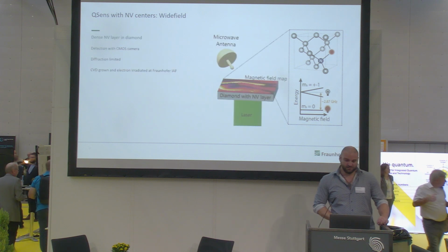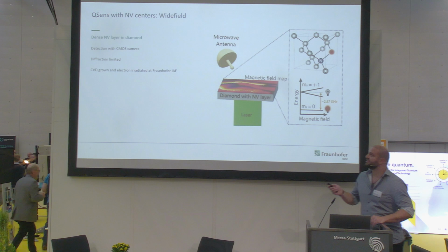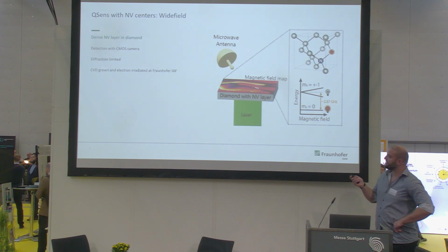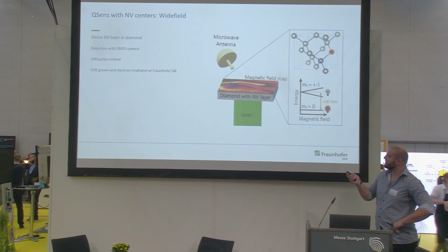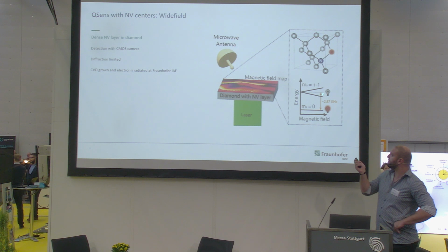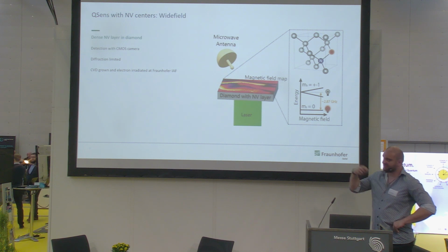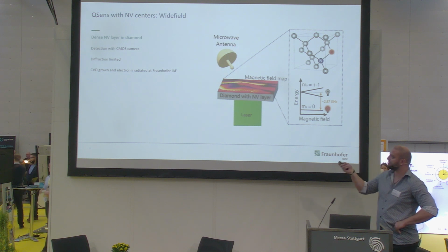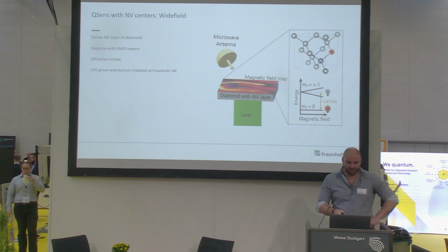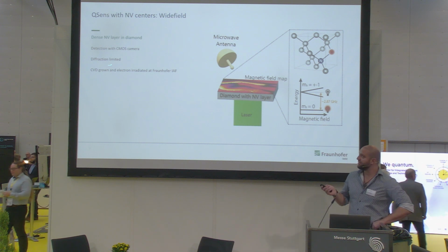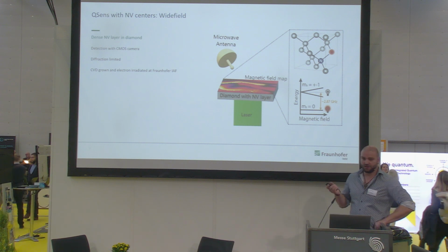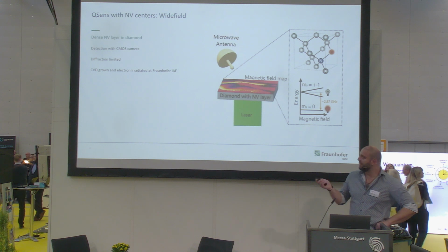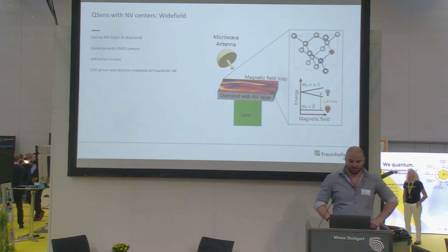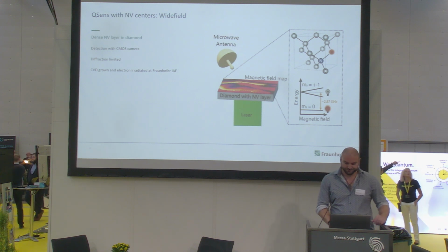So the wide field itself, it's like we have the diamond with a dense layer of a lot of NVs. We shine the laser and we apply microwaves to shove around the spin between the states with a microwave antenna, which is just irradiated from the top. So the setup is diffraction limited, so we get down to whatever our optics allow us. And the diamond itself is CVD grown at IAF, and it's also irradiated with electrons.